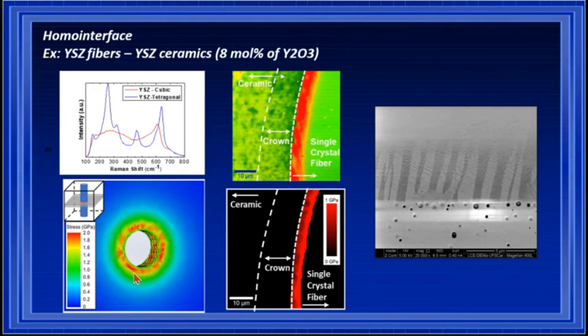If we do a thermomechanical analysis simulation of the sintering process, we can see that the pressure can go as high as 2 gigapascal. At room temperature, we can correlate the Raman shift of the tetragonal phase with pressure, and we can show that in this region the pressure can go as high as 1 gigapascal. In this way, this could be a method to produce self-strained interfaces, which could also be one of the reasons to enhance the ionic conductivity in zirconia materials.